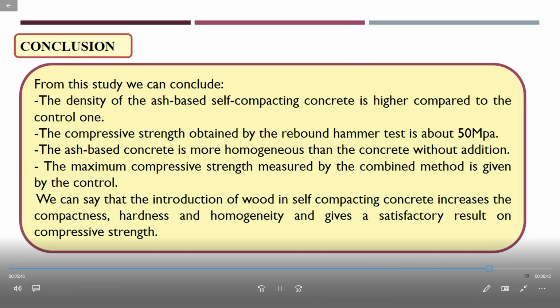In conclusion, from this study, we can conclude that the density of the ash-based self-compacting concrete is higher compared to the control one. The compressive strength obtained by the rebound hammer test is about 50 megapascals. The ash-based concrete is more homogeneous than the concrete without addition. The maximum compressive strength measured by the combined method is given by the control. We can say that the introduction of wood ash in self-compacting concrete increases the compactness, hardness, and homogeneity and gives satisfactory results on